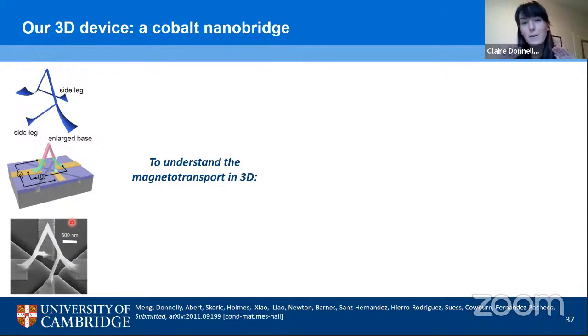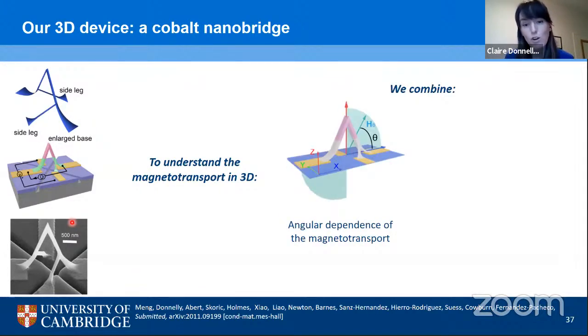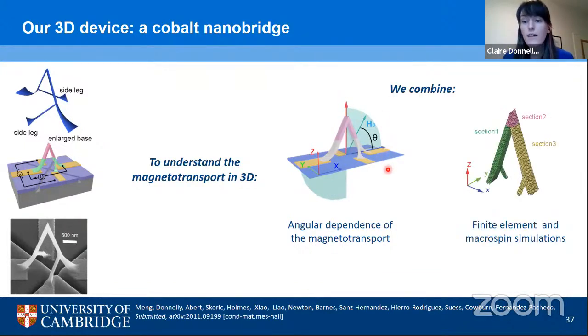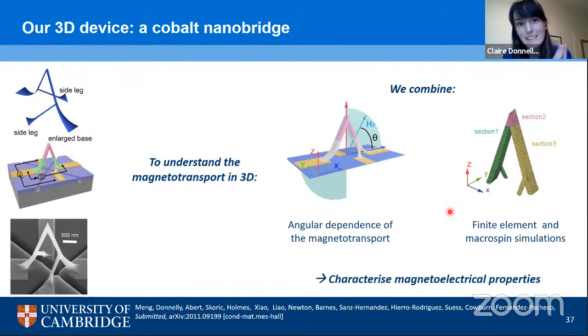Now, in order to understand the magnetotransport in 3D, similar to our X-ray measurements, we need to measure the properties from many different orientations. And this is what we do. We combine the angular dependent measurements of the magnetotransport, by applying magnetic fields for many different orientations with respect to the 3D structure, with finite element and macrospin simulations that aim to simulate the magnetoresistance of our bridge. And in this way, we're able to characterize the magnetoelectrical properties and identify the influence of the 3D structure on the magnetoresistance.